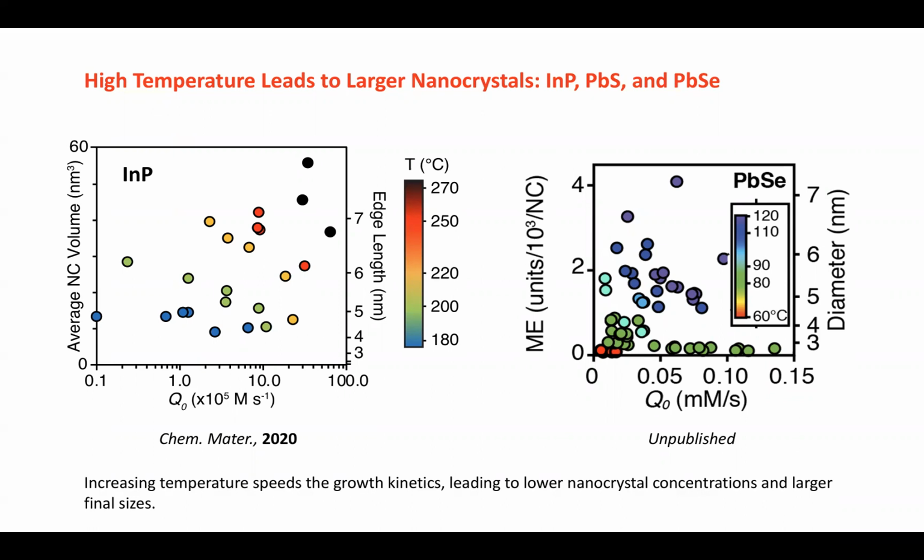So this observation is consistent with the claim that you let the horses out of the gate slowly, but the small ones grow more readily than the big ones do. That's consistent with the polydispersity being defined by the difficulty of growing a large crystal and the ease with which small crystals grow. So crystals naturally pile up in narrow polydispersity because it's harder and harder to grow them the bigger they get. Now, eventually this stops because a micron-sized chunk and a 1.1 micron-sized chunk are identical. Surfaces are very similar. But down here at this very small scale, that's not true. These are almost molecular.